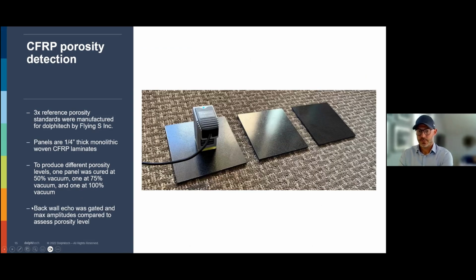Now, one that's quite interesting for this group is the porosity detection in composites. Since we have so much data, this gives a tremendous opportunity to inspect porosity. Not just like a spot check of porosity, but you have to remember we have 16,384 measurement points within this transducer front here. So you can see the variation of the transducer as well. So what we did here is that we had someone produce something composite with 50% vacuum, 75% vacuum, and 100% vacuum.